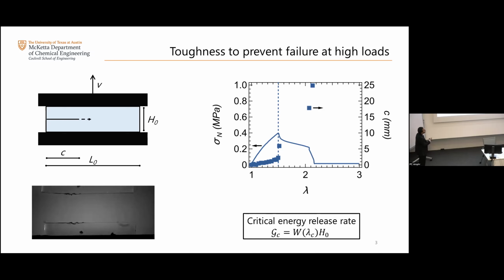And while you conduct that experiment, what you do is you record the stress and the stretch. So here what you have is the stress-stretch curve. And eventually you reach a critical point at which the system fails. And then what you can do is actually integrate this curve all the way to the fracture point to calculate what we call the strain energy density, which is a measure of how much energy you're storing in the material up to the fracture point. And then you multiply that by a geometric factor. In this particular case, it's the spacing between the clamps because of the geometry of the system. And then you get a critical energy release rate, which is a critical amount of energy that is released when you propagate your crack. Okay, so that's a typical experiment that you do. And again, it's an experiment that takes the material all the way to the fracture point.